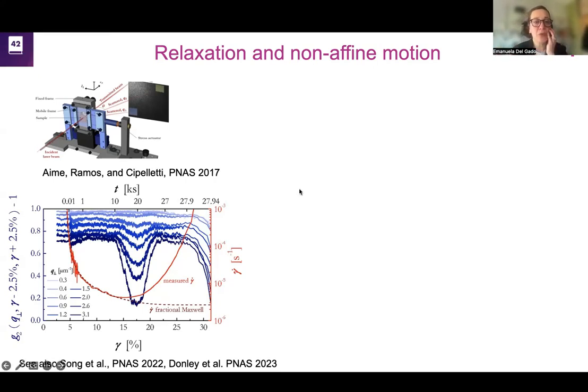And this is an example that I wanted to show you because precisely in this experiment, Stefano Aime was able to show that this is a creeping gel where they had applied a stress and watched the system eventually start to flow. And as it was failing, they could see that before the system actually fractures, there is a precursor of the fracture and the failure of the system that will happen macroscopically, in this microscopic motion. So the blue data is in fact the intensity of the amount of the non-affine motion that is seen through the shear cell, and the red data are the macroscopic rheological response. So you can see that there is this connection to build.